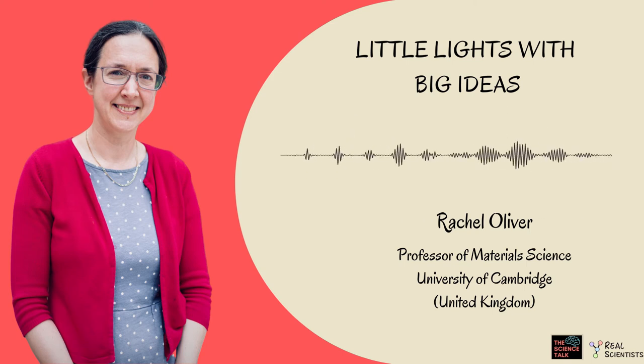some of them in Oxford, some of them elsewhere, realized that you could hold the tip at a steady voltage, and instead of having a pulse in the voltage, you could apply a little pulse of laser light. So you could just warm up the atoms a tiny bit with a little bit of laser light in a pulse and have the same effect. So now we do laser pulsed atom probe, and we use the laser to pulse. We know the time of the laser pulse, and we see how long it takes from the laser pulse for the atom to fly to the detector.